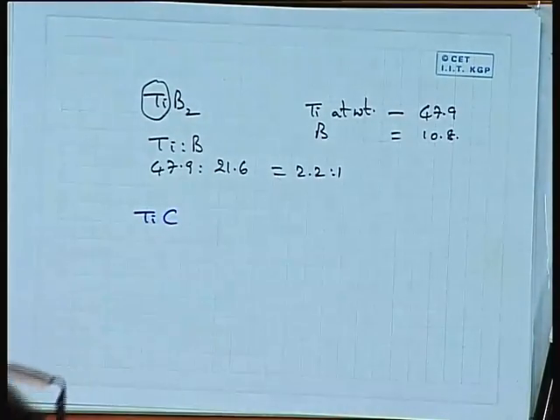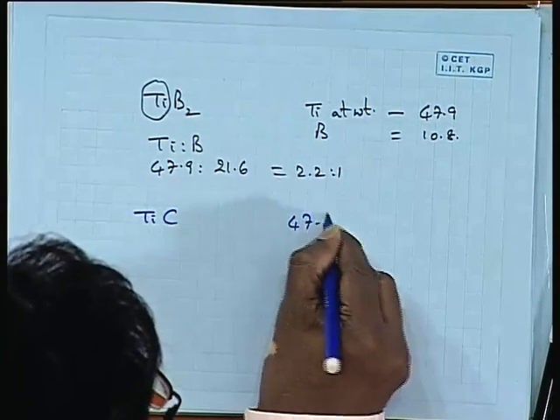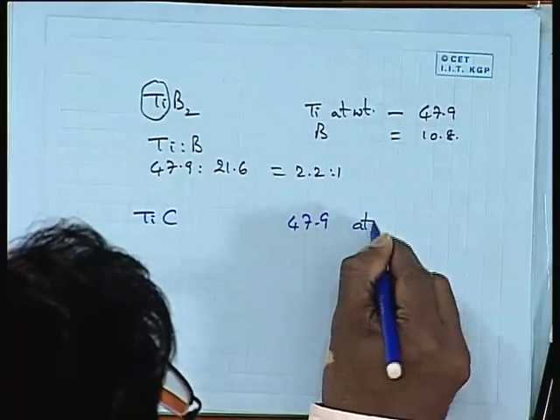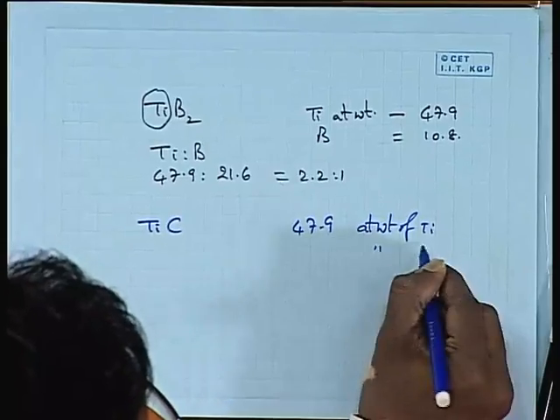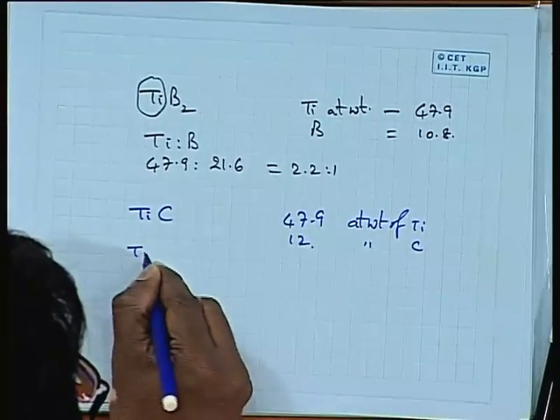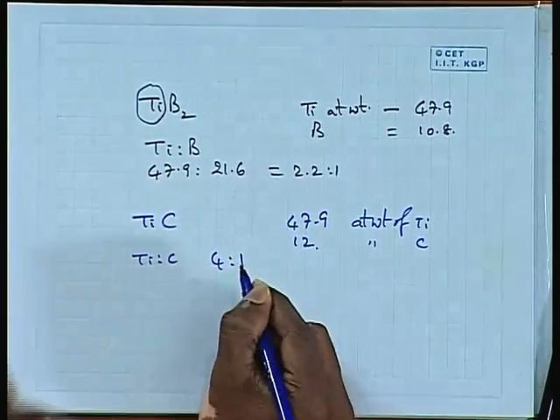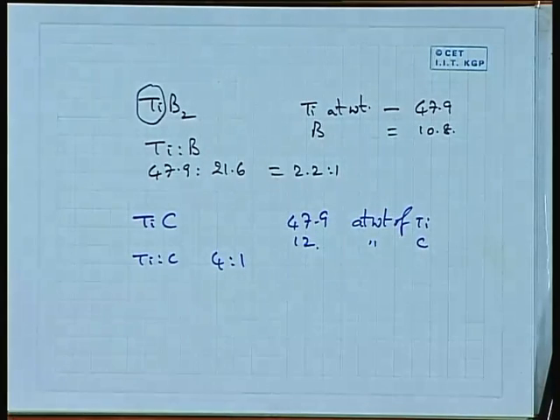This is another class of new generation composites, where again a similar situation, you need titanium and you need carbon to form TiC. And what is the ratio here? If you again look at TiC, titanium atomic weight we have already seen 47.9. What is the atomic weight of carbon? Okay. Atomic weight of carbon is 12. So, the ratio of Ti to C that we need here is of the order of around 4:1, is it not? So, if one can have a ratio of about 4:1, one can again control to give you only TiC particles. The interesting feature of TiC is that it is a cubic phase.